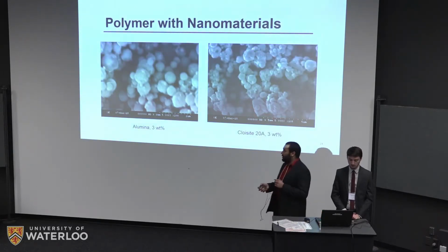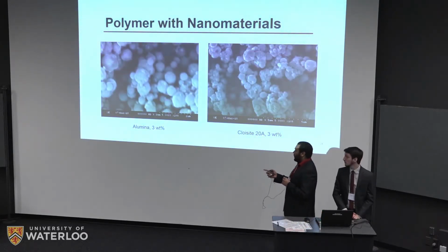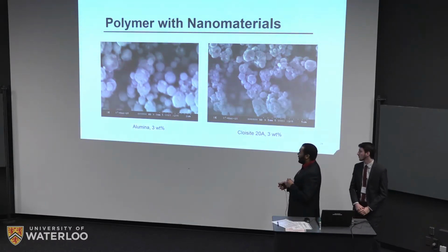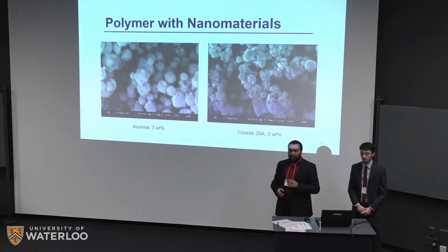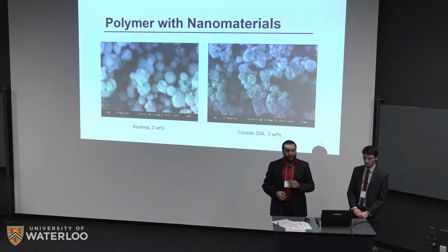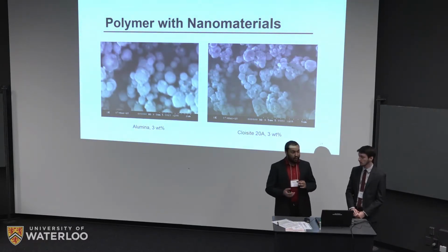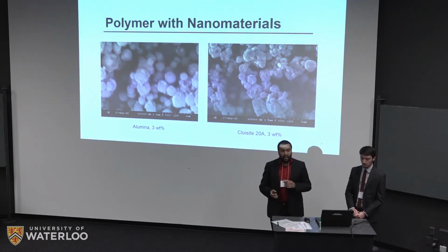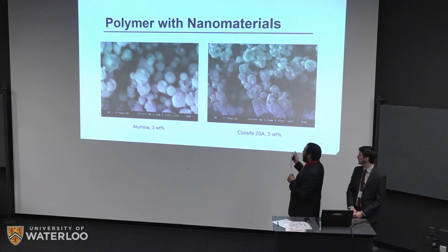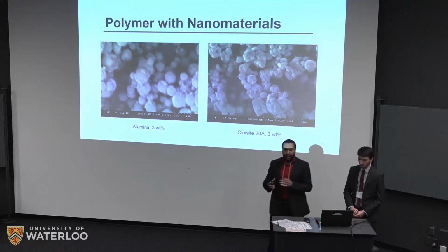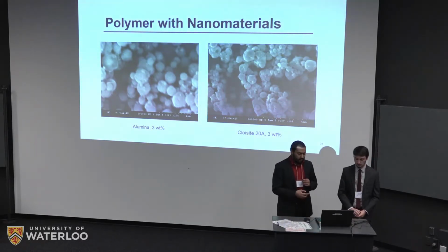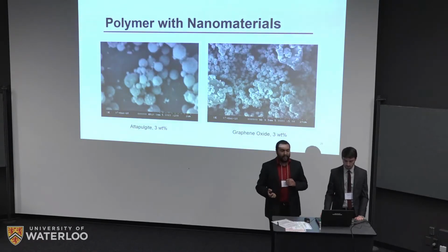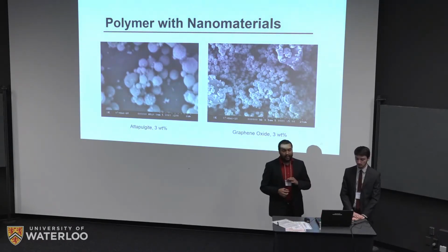Some of these images here are alumina, 3 weight percent, and Cloisite 20A, 3 weight percent. One of the major takeaways from these images is there are no huge aggregates of material. You can see the spheres, and they have a fairly uniform morphology, but we don't have pockets of nanomaterials and pockets of spheres. It's pretty well dispersed throughout. And same thing with the attapulgite and graphene oxide.